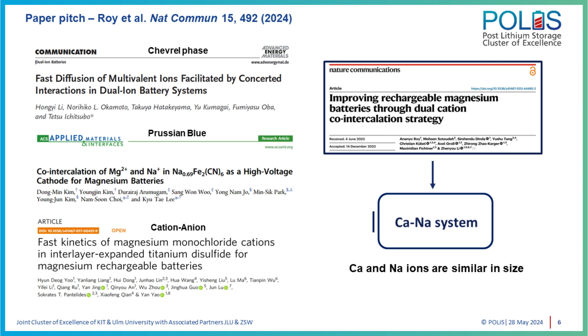So we don't know, for a cubic Prussian blue structure, how the structure plays a role in a potential co-intercalating setup. There was another nice work done with TiS₂, but that was co-intercalation of not two cations — which is our work with dual cations — but a cation and an anion: insertion of magnesium chloride complexes, almost Mg²⁺ and Cl⁻. That work also showed that co-intercalation concepts are quite diverse — different structures, different concepts, but all under the umbrella of co-intercalation.